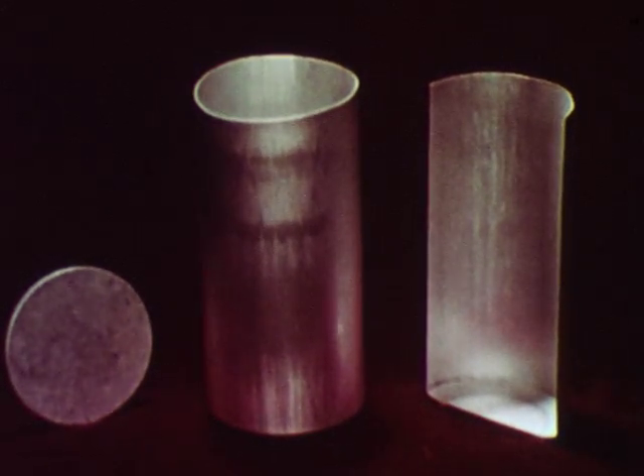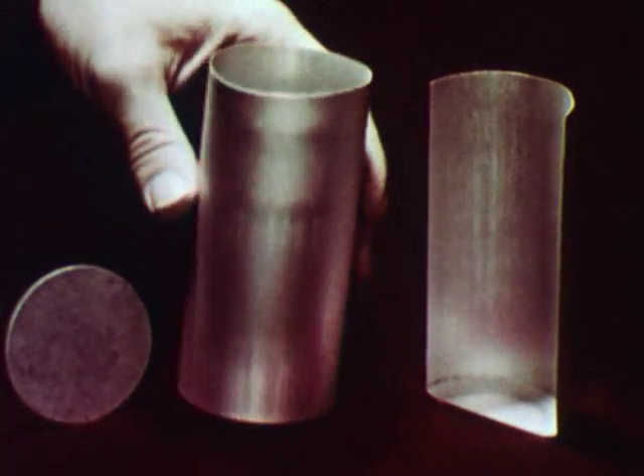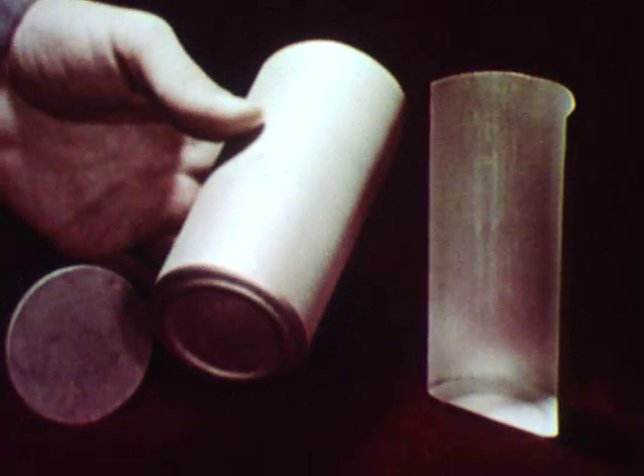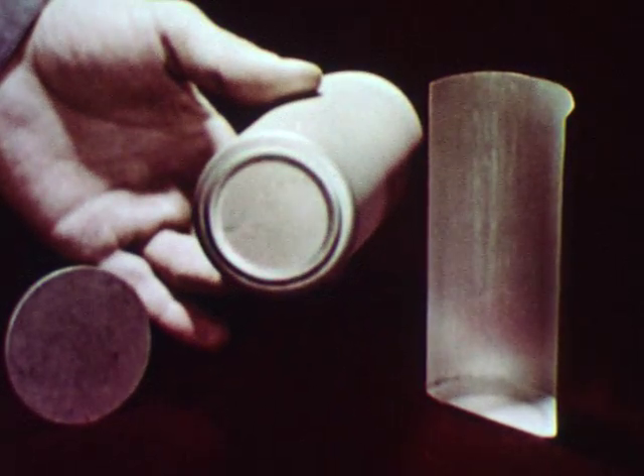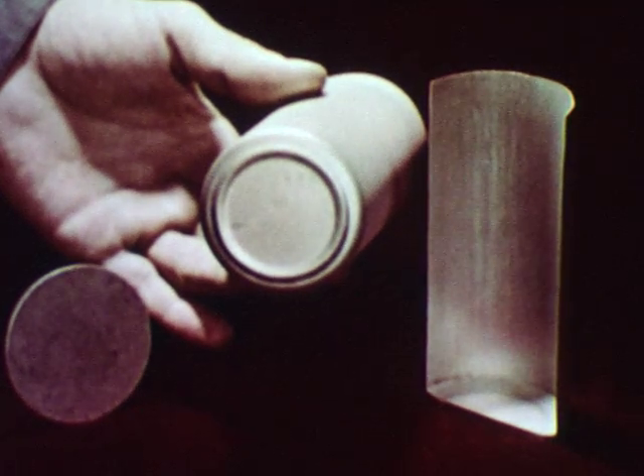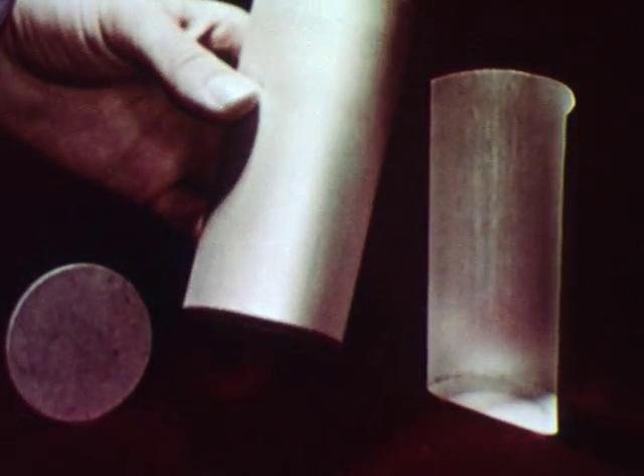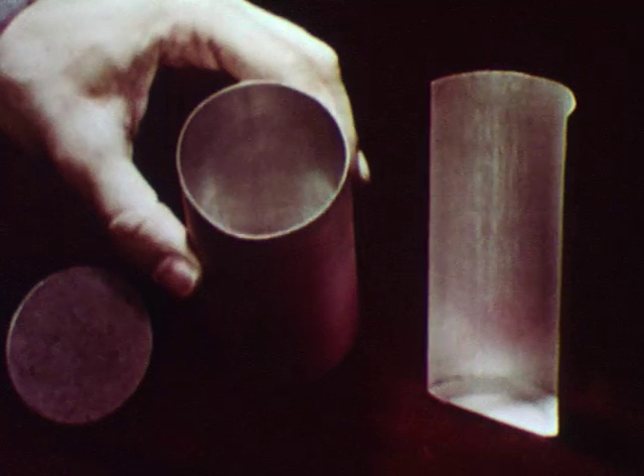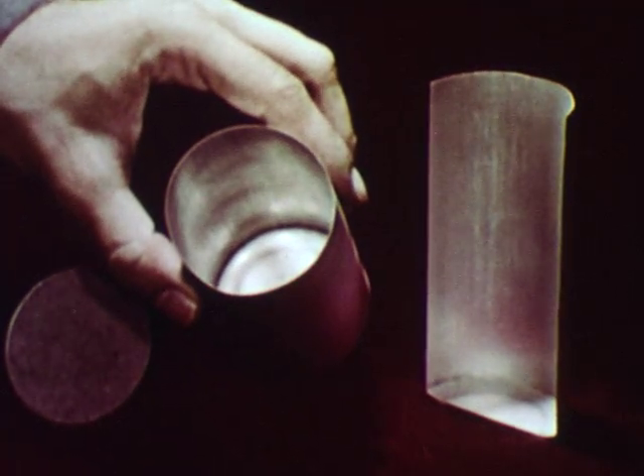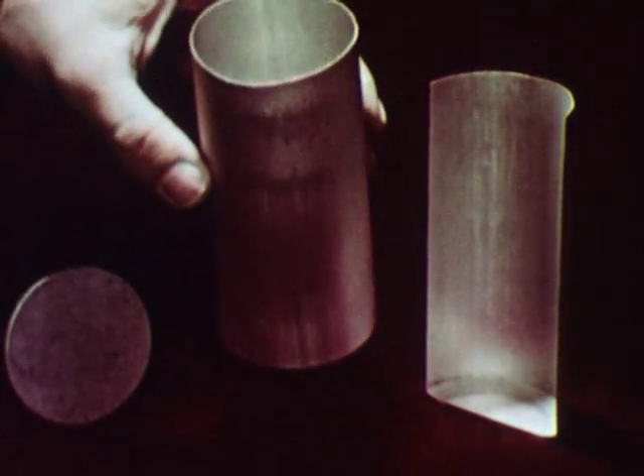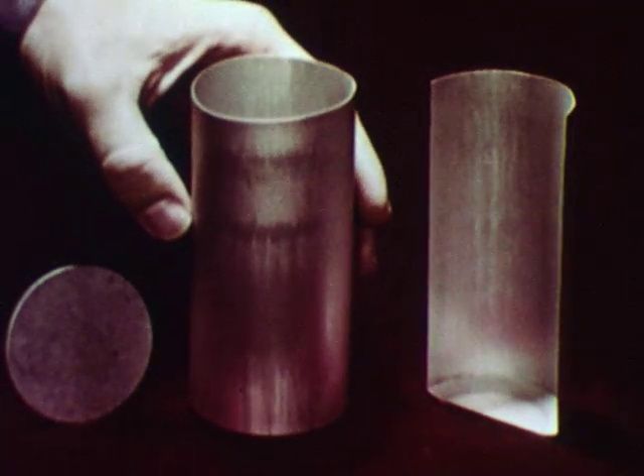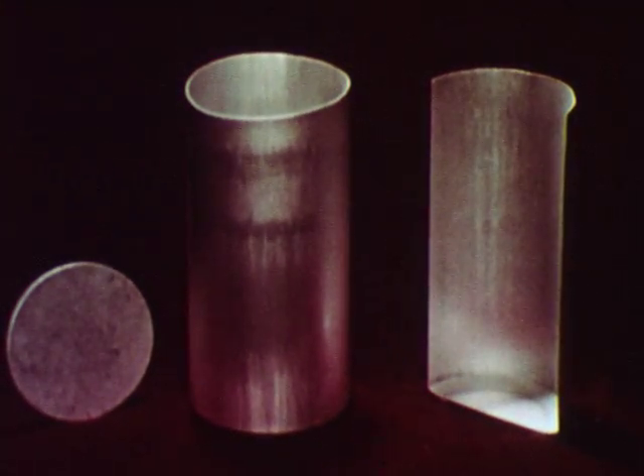In still another area of cold forging's ever-changing frontier, we see the seamless aluminum can. It could be a case, a cover, or any hollow component. This 11-ounce seamless aluminum beer can is made at rates up to 240 per minute on a 400-ton horizontal extrusion maxi press.